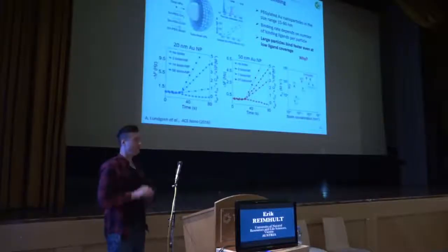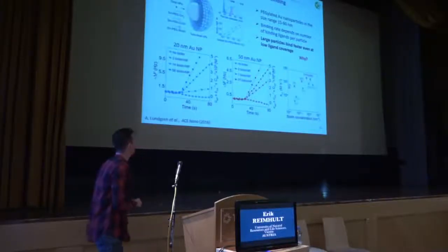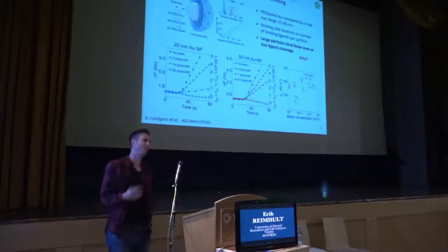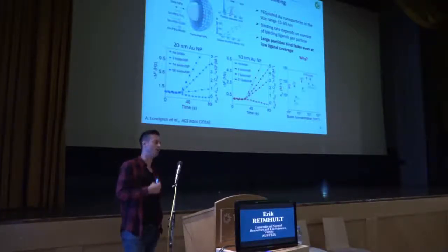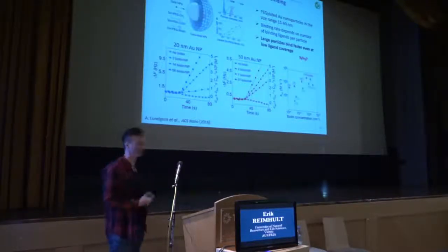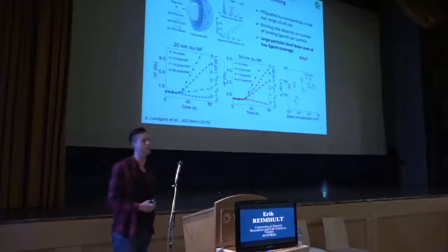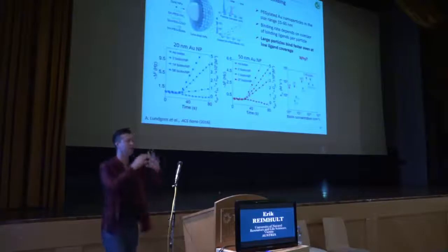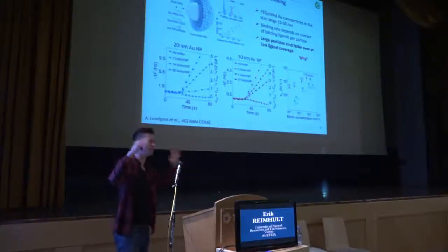So we made these two particles. Actually, we tried to not make them too perfect because we wanted to look at differences. So we have a slightly lower grafting density of these polymers than we can optimally achieve, for example, to make the linear polymer particles good. But if we make them all the same molecular weight, same grafting density, we observe the following in terms of colloidal stability. Big core, 20 and 50 nanometers, and then we have a polymer shell, PEG shell, that makes them colloidally stable.